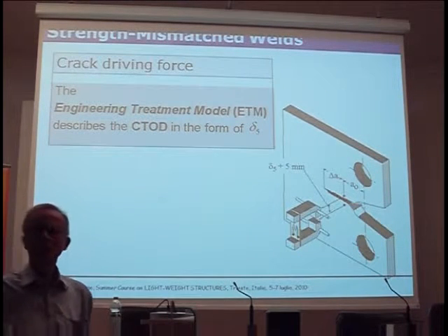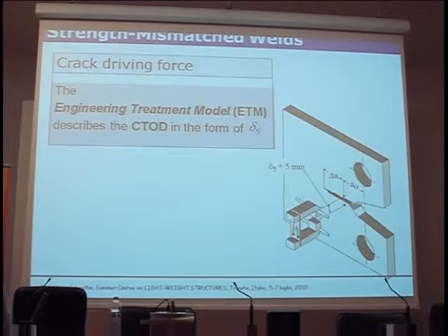When we have an open door day at the institute and the people come and see the tests, they can't believe that the specimen doesn't go bang, you know. If you do a load control test, the specimen goes bang at a certain point, of course, because you can't increase the force anymore. But if it's strain controlled, you can drive the crack all the way through until nothing is left. So this is like rubber. Metal can really behave kind of like rubber.